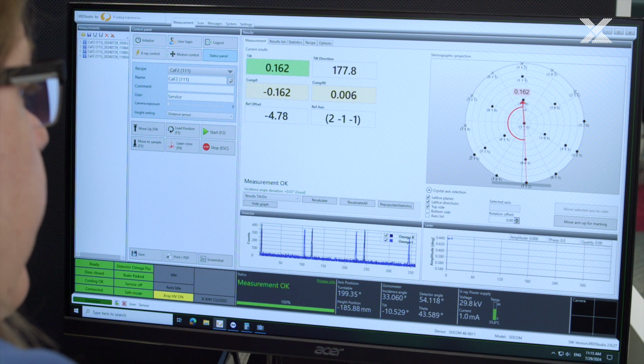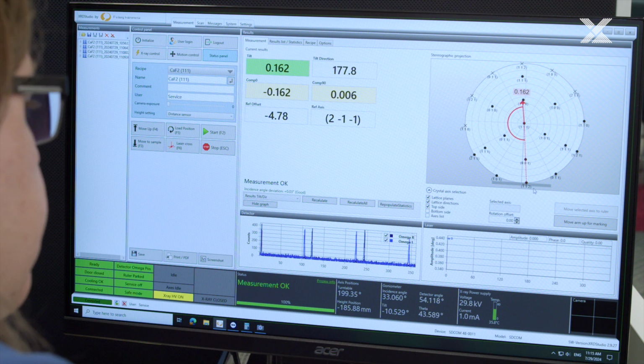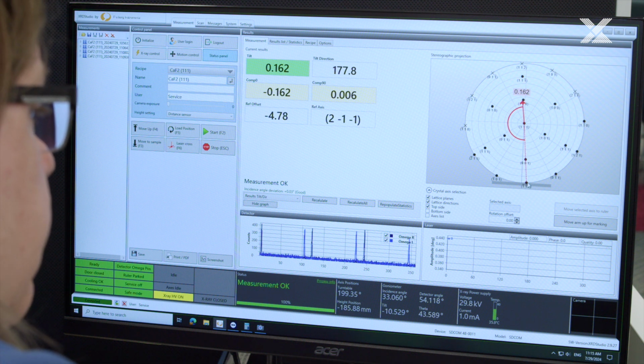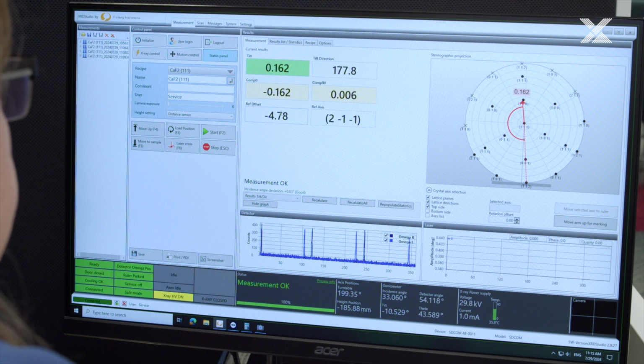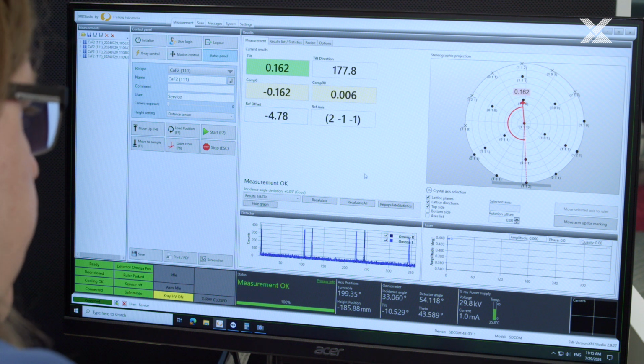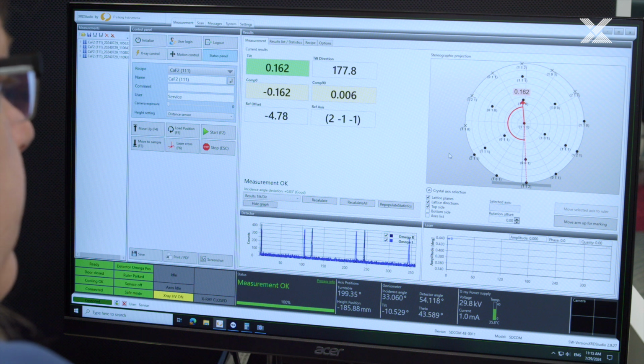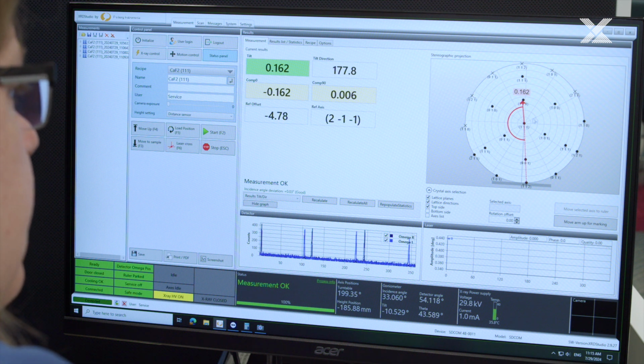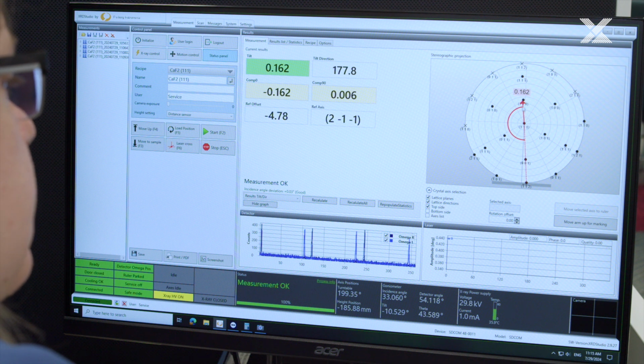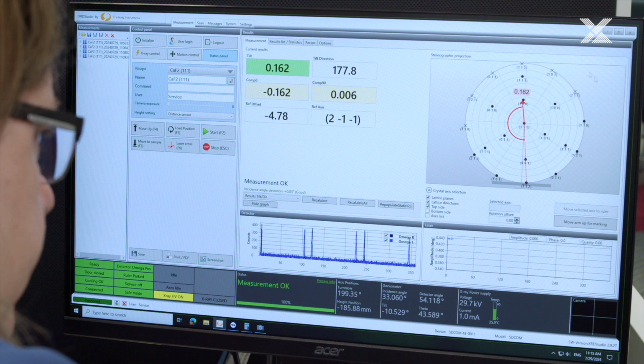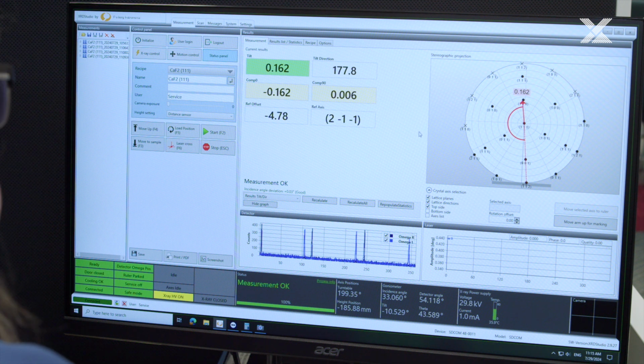We can see that we're almost 90 degrees away from the -1, -1, 2 direction, and the angle between the -1, -1, 2, and the center position on the bar here is 4.7 degrees. That was measured here. So we can also very accurately measure all these in-plane directions. With many other X-ray crystal alignment techniques, you would only get where the tilt is pointing, but you would not get all these other crystal directions at the same time.